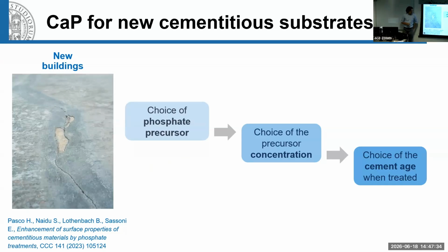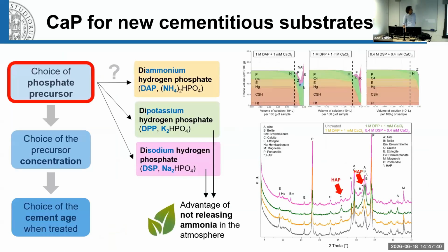In collaboration with a company, Saint-Gobain from France, that was interested in this technique, we first screened different phosphate salts as precursors for the formation of hydroxyapatite. So as an alternative to DAP, the diammonium hydrogen phosphate, we considered potassium phosphate and sodium phosphate, because in this case the advantage would be that we do not release ammonia in the atmosphere, which is good. Releasing less ammonia is good from the environmental point of view, and also in terms of smell, which the restorers, the people that perform these treatments, can smell.